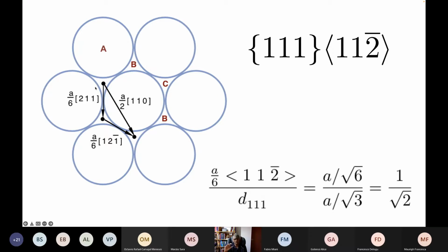Okay, and the distance over which that displacement happens normal to the close-packed plane is the spacing of the 111 planes, which is a/√3. So the twinning shear is simply the displacement divided by the height over which it happens, which is 1 over square root of 2, or 0.7071. So that is a very large shear deformation. If you recall my lectures on martensite and bainite and so on, the shear was only about 0.26. This is 0.7071, or 1 upon √2 to be exact. So twinning involves very large deformation, and that's why mechanical twins will always form in the form of very thin plates in order to minimize the strain energy.